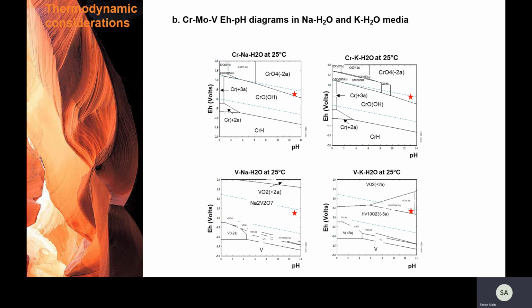Under this condition, in the presence of sodium hydroxide and potassium hydroxide, chromium forms chromate, and in the case of vanadium, sodium or potassium vanadates are the phases likely to be formed. All this collected information seems to confirm that treatment of slag with the chosen alkaline reagents allows obtaining a water-soluble compound containing the targeted metals. Such high solubility in aqueous media should be an important element to facilitate recovery of such metals.